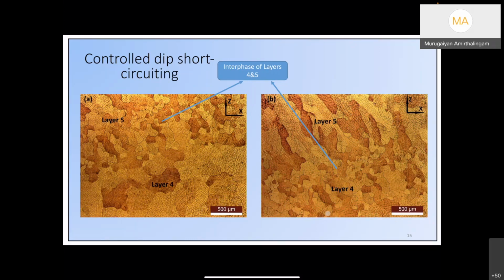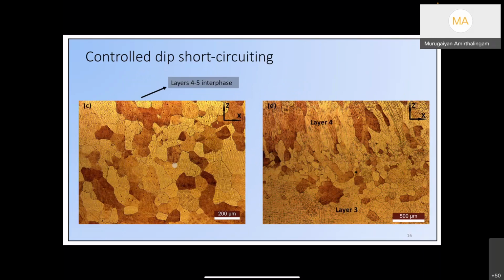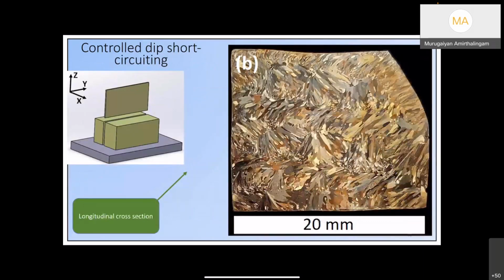So now we see here, obviously, the microstructure we get is an equiaxed dendrite microstructure. And the microstructure is as good as any forged microstructure, right? The forged microstructure, what you see in a conventional way, would appear similar, right? That will also be reflected in the mechanical properties. So when we look at the mechanical properties, we expect that this would perform better. So how do we achieve it?